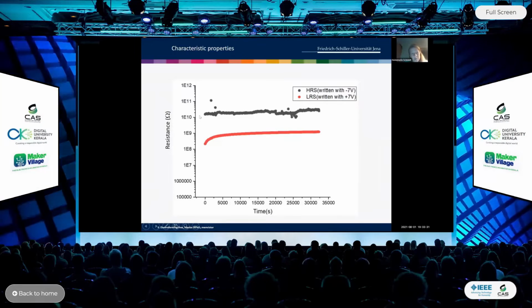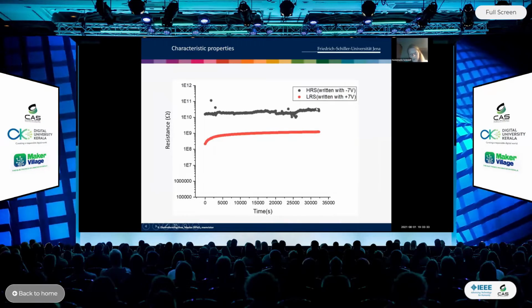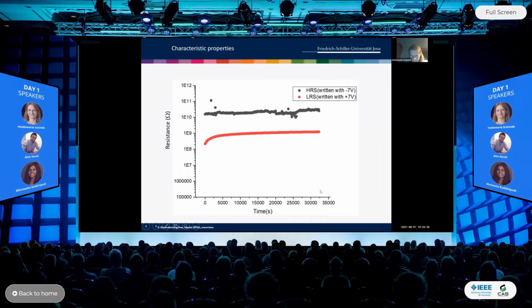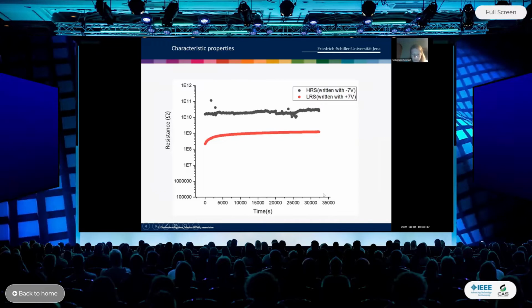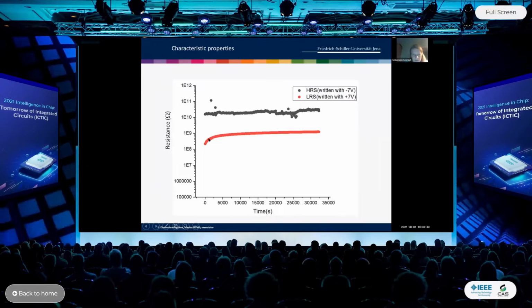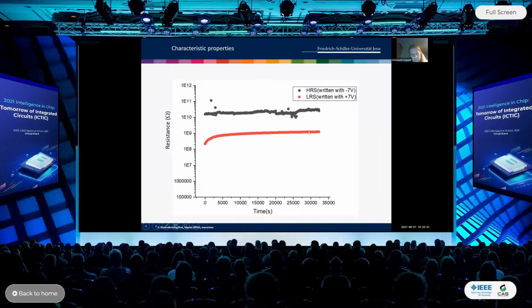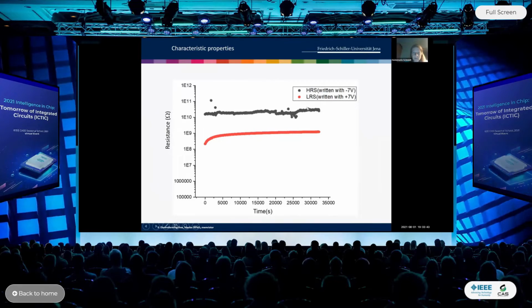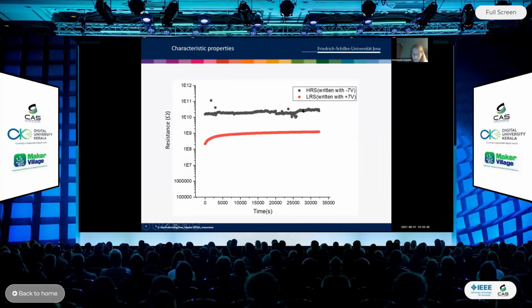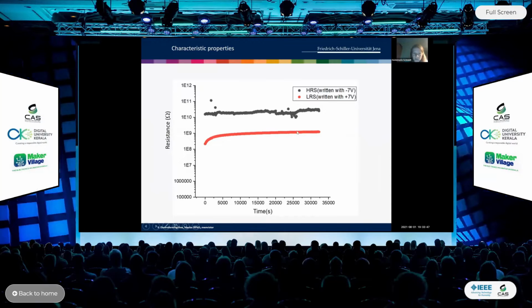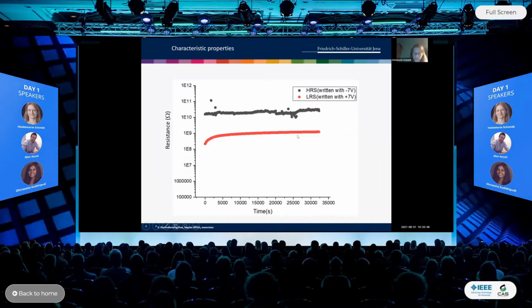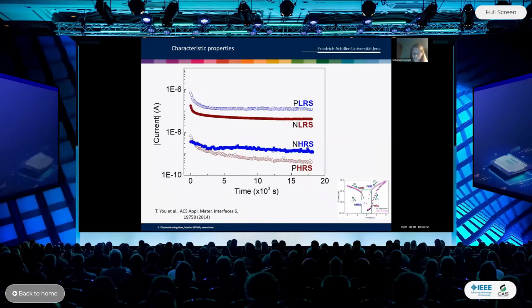This is the resistance in the high resistance state, which is read out over a time of up to 35,000 seconds. And the low resistance state retention looks like that. And the ratio between the resistance in the high resistance state and in the low resistance state is larger than 10. This is a condition which has to be fulfilled.